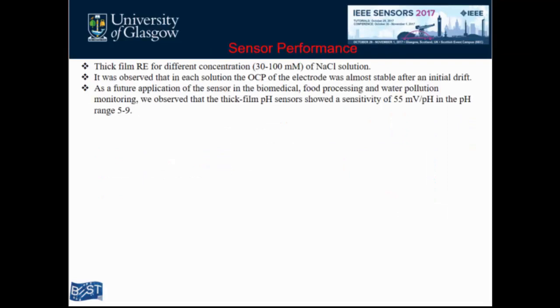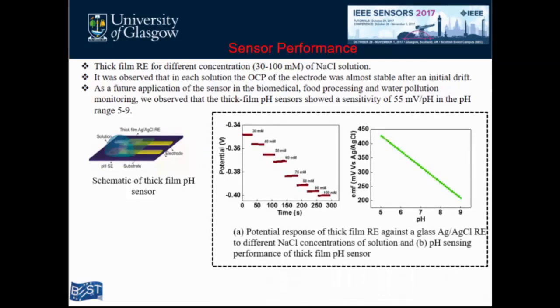And for an application of this reference electrode, I developed a thick film pH sensor based on a sensitive layer. It's a ruthenium oxide sensitive layer, and the potentiometric performance of this pH sensor was measured, and we observed a sensitivity of 55 millivolt per pH in the range of 5 to 9, and I also characterized it in the range of pH 2 to 12. I also did this work.